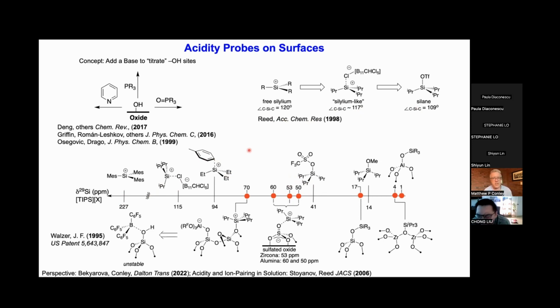To be clear, this has nothing to do with charge on silicon. This has everything to do with the structure you're obtaining, because the silicon NMR chemical shift is related to the coupling of the silicon carbon bond to the empty p orbital on the silicon. And as you approach a 90-degree relationship between the silicon carbon and the empty orbital on silicon, you reach that sort of maximum paramagnetic deshielding that results in these chemical shifts.